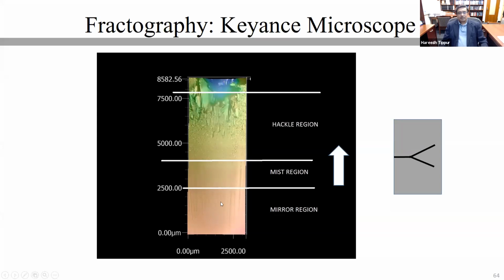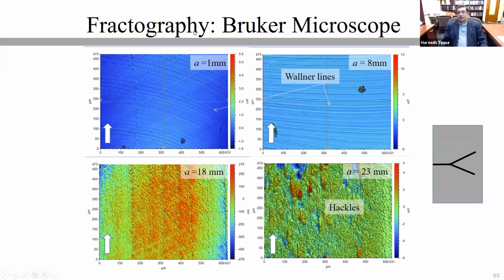Unfortunately, the resolution of this digital microscope was not good enough for us to extract the roughness in the mirror and the mist region very accurately. Of course, we could get information in the Hackle region, which is reasonably valuable. Therefore, we switched over to another microscope, which is a nanoscale resolution microscope. This is again a digital microscope.